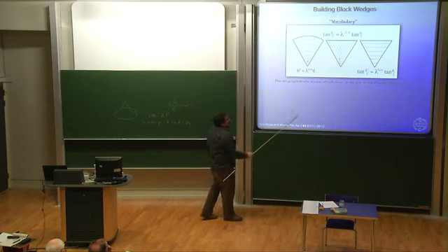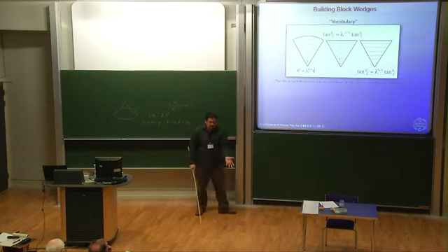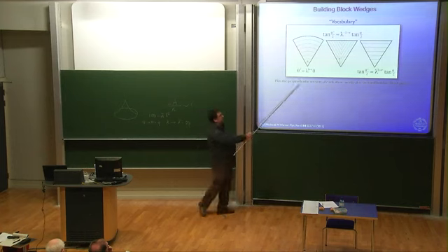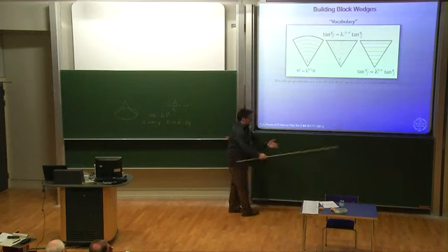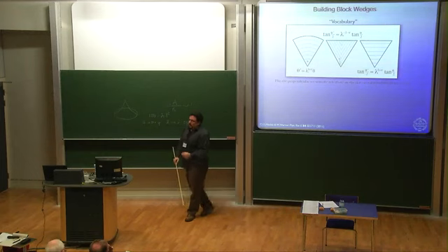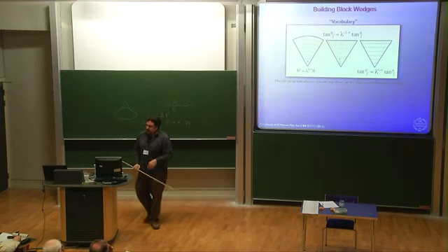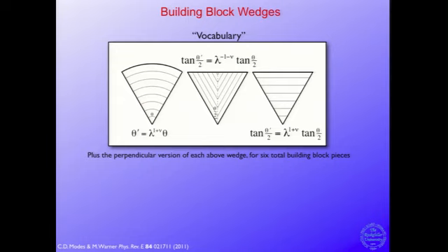For each individual piece, you can imagine just having that piece, an isolated triangle of nematic glass, like this, and like this, just sitting on a lab table. And you can imagine heating it or straining it. And you can see very quickly what's going to happen is that the lateral extent will change somehow, and the opening angle of the cone will change somehow. And you can calculate what the new angles are as a function of the imposed strain.